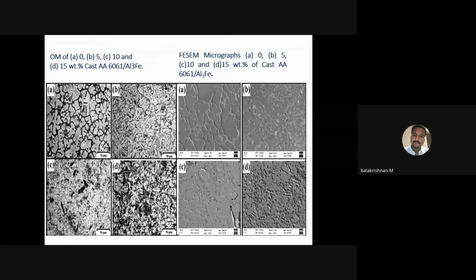As the content of Al3Fe particle increased beyond 5 weight percentage... as I already discussed, the minimum quantity is 5, because if we go for 4, 3, or 2, the magnesium compound will form a dendritic structure due to the presence of magnesium and silicon. That's why we are going for 5.